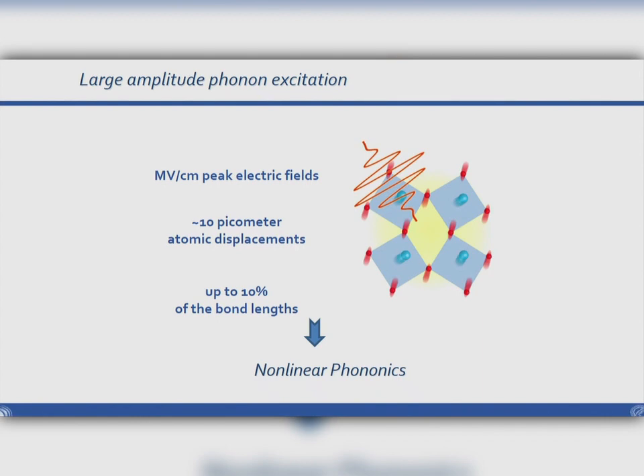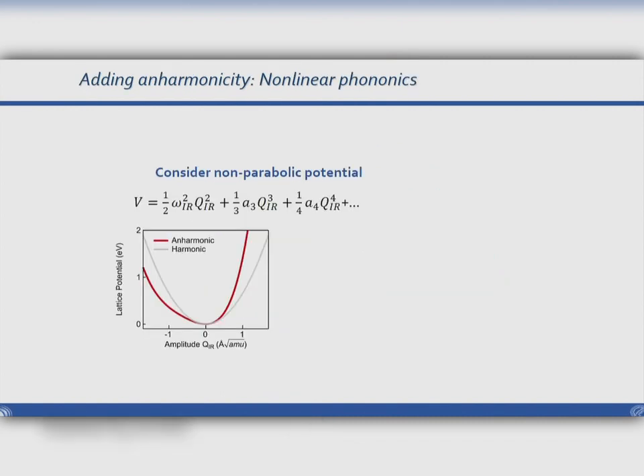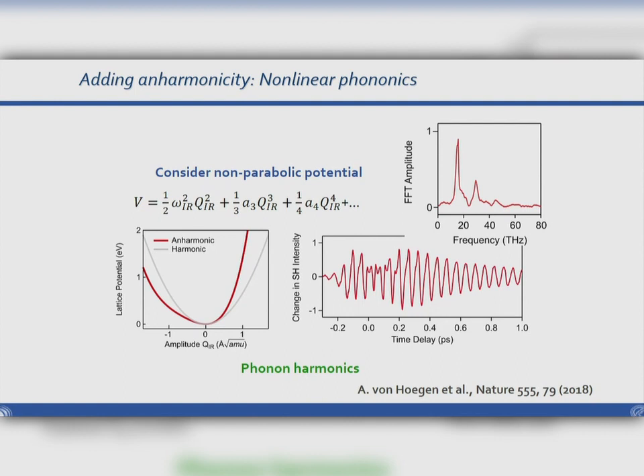And in this regime, you end up in a situation where nonlinear interactions of the atomic motions become important. And this we can also measure, as highlighted here. This is the same experiment as shown before, but just with a much, much stronger electric field. And what you see here is you not only observe harmonic oscillations, but particularly here, where the amplitude of this oscillation is very large, you see that higher frequency components appear. And this is due to the fact that now you drive the system into a range of amplitudes where the anharmonic terms of the potential have to be taken into account. And this then leads to high harmonics also in the motion of the atoms along this coordinate. So nonlinear phononics is real.